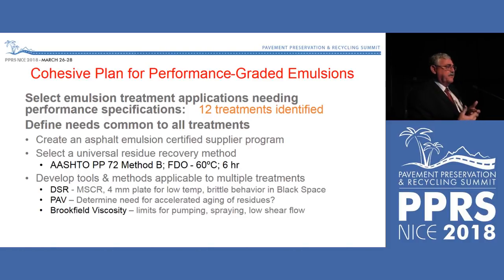And the DSR is perfect because we can wad off a little ball of our recovered residue without reheating it, put it on the DSR and condition it and test it. But we're finding we can do many more things than frequency sweeps with the DSR. We can use creep recovery tests at multiple stresses if we like. A 4-millimeter plate geometry now allows us to replace the bending beam rheometer and define low temperature rheological properties with our rheometer. We can determine now brittle behavior.